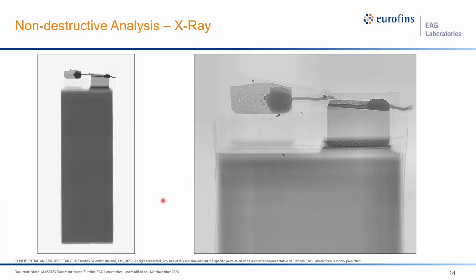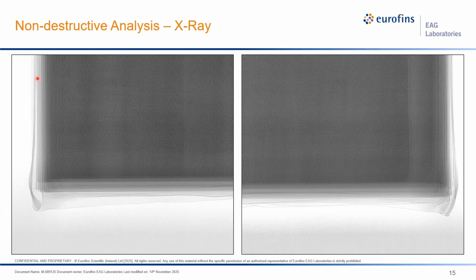And then we look for any unusual aspects in the cell, such as the rigidity of the tabs, or how is the jelly roll standing? Is there any crack in the electrodes or components? So we look for these kinds of things, and also any region that deformed more than the other portions. And we can also zoom into certain regions, especially the edges and corners, which are more prone to start failure mechanisms because of the additional mechanical stress that they are experiencing during the operation. So we can also zoom into different areas if needed, and then look in more detail for those areas.